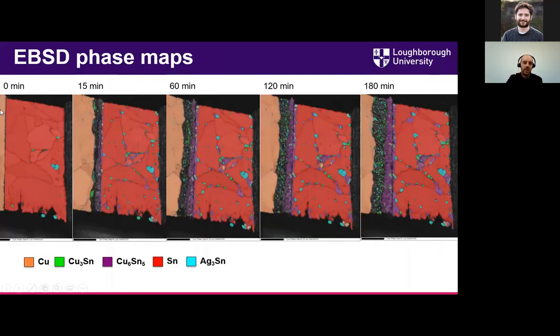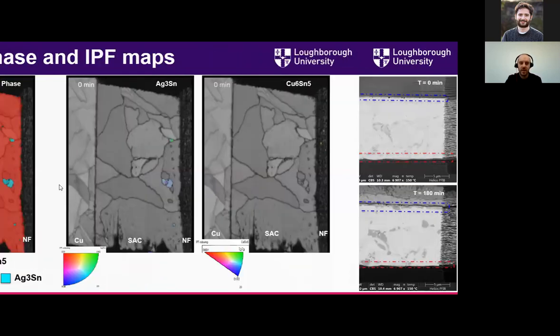Okay. So looking at this with the EBSD, what we can do is track what phases are where within the joint, and also what their orientation is, what their size is, and what phase we have. So over time, you can see at the start, we just have a few silver precipitates and not really any intermetallics formed at the copper or nanofoil grain boundary. And then quite quickly, we start to form intermetallics at the grain boundaries and also start to grow intermetallics at both faces. Then over time in the bulk, we start to see some of the intermetallics joining and forming larger and larger grains. And at the copper face, we see the Cu6Sn5 actually traveling across the surface and forming intermetallics across the copper, which was quite unexpected. You wouldn't necessarily expect to see this.